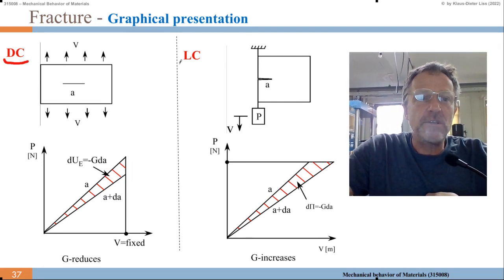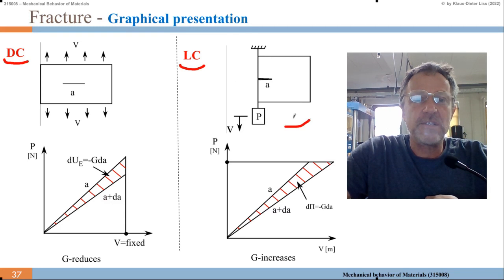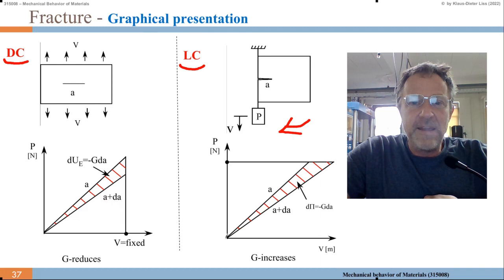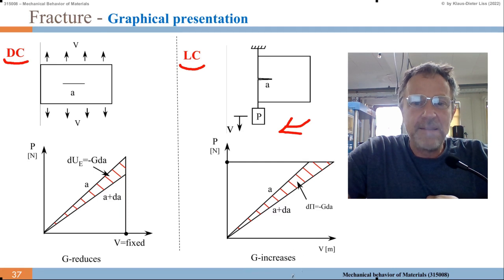We have displacement control and we have load control. I just mentioned load control. So if I have a crack length A, then this is my pi, the upper triangle here. Now I increase by dA, and of course the slope changes. I get this d pi, which is minus G dA. That means G increases with increasing A.